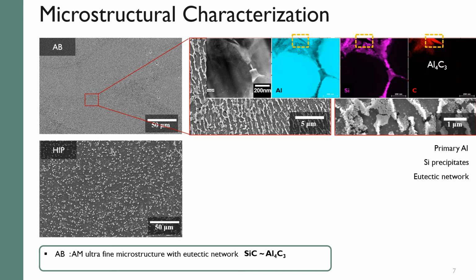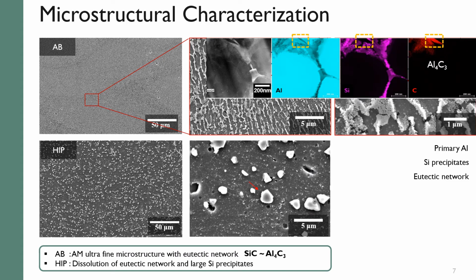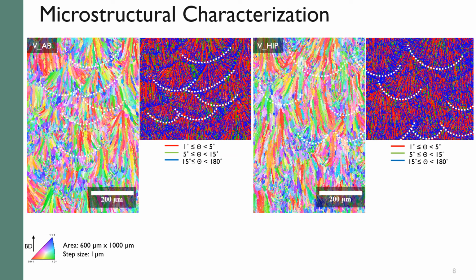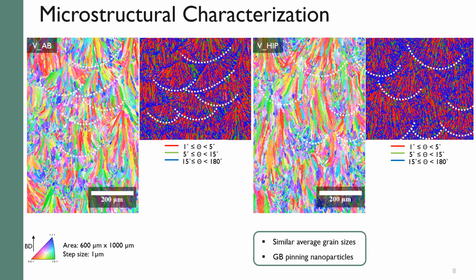And for the HIP condition, we observe a much homogenized microstructure, dissolution of eutectic network, and coarser silicon precipitates. When we have a look at the EBSD maps for as-built and HIP samples, no significant grain growth is recorded after HIP, which can be due to the grain boundary pinning of nanoparticles.